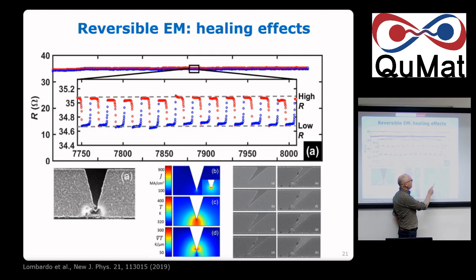You see there is a small black spot there. Those black spots are materials removed. But if you look carefully, there is no current density over there. So you move atoms even where there is no current, because you build up stress in the system as well. Besides electromigration, you have migration due to gradient of concentration and due to the gradient of temperature, thermomigration as well. So there are many effects that play a role.